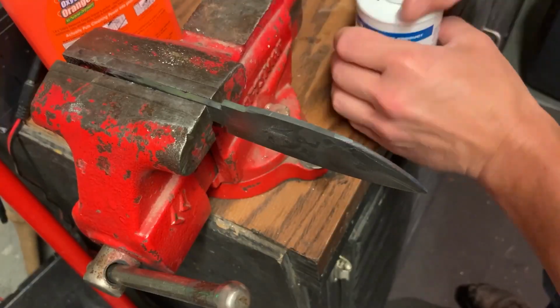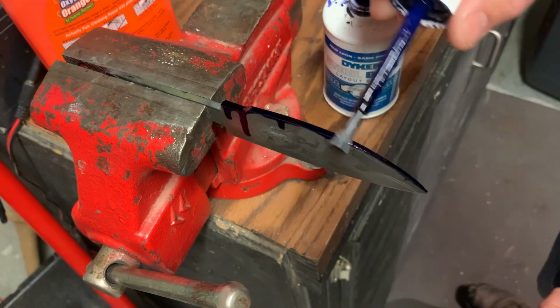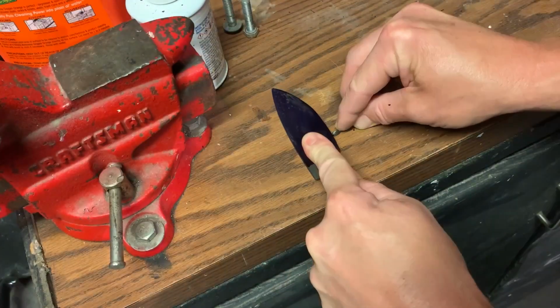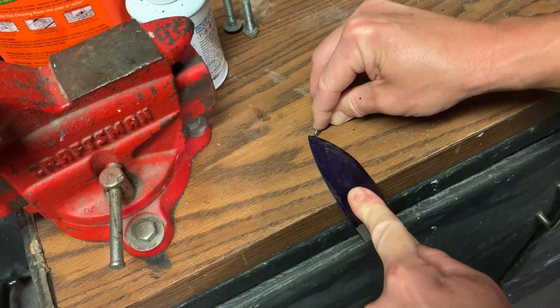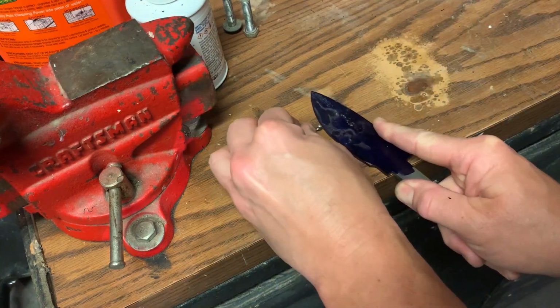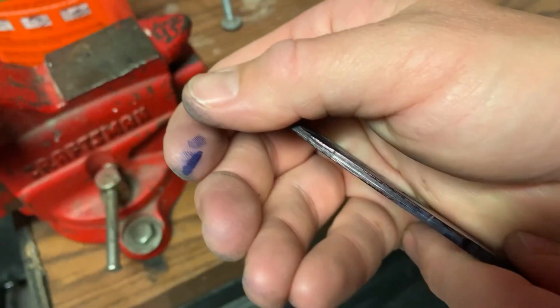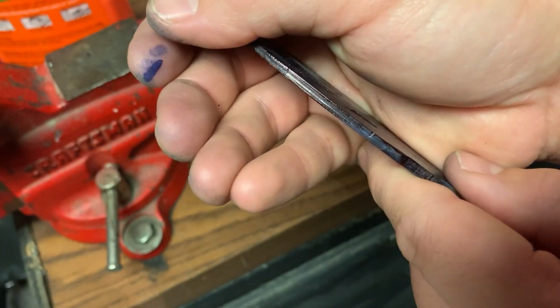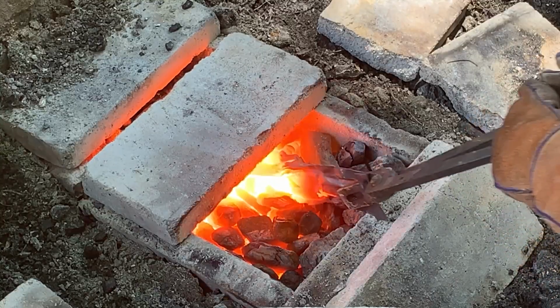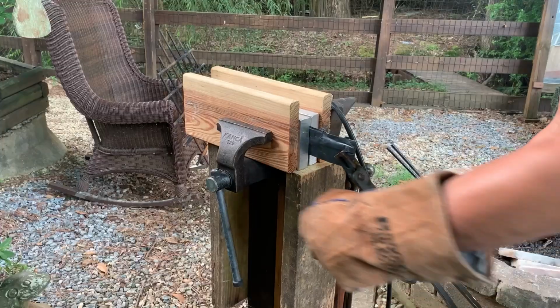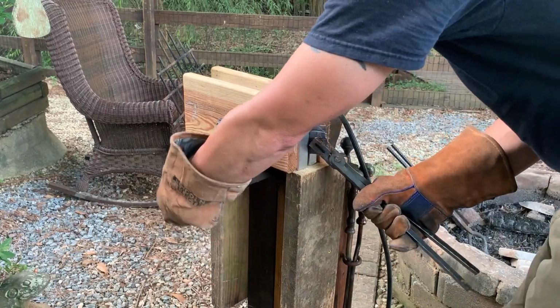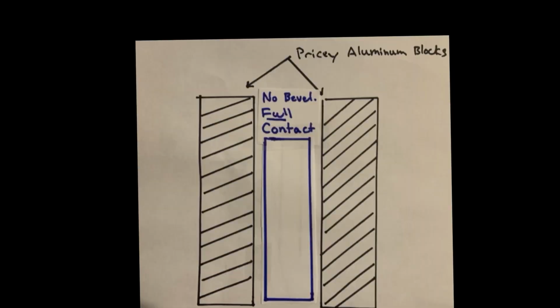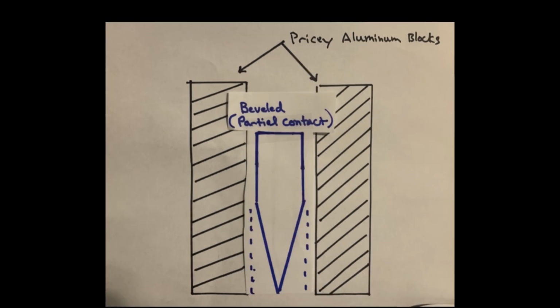Now I'm coating the blade in layout fluid and using a drill bit of equal thickness to scribe a center line down the belly. So if you're wondering why I waited until after heat treatment to grind any bevels, the reason is due to the plate quenching. When the red hot blade is sandwiched between the plates, there needs to be as much surface area as possible making contact with them, to conductively transfer as much heat as quickly as possible. To grind bevels ahead of time would not only slow this down, but make it where the part of the blade which most needs quenching failed to contact the aluminum.